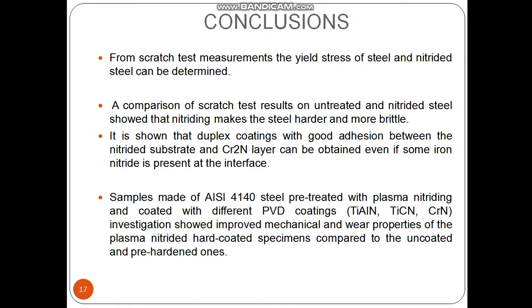Conclusions. From scratch test measurements, the yield stress of steel and nitrided steel can be determined. A comparison of scratch test results on untreated and nitrided steel showed that nitriding makes the steel harder and more brittle. It is shown that a duplex coating with good adhesion between the nitrided substrate and Cr2N layer can be obtained even if some iron nitride is present at the interface. Samples made of AISI 4140 steel pre-treated with plasma nitriding and coated with different PVD coatings. Investigation showed improved mechanical and wear properties of the plasma nitrided hard coated specimens compared to